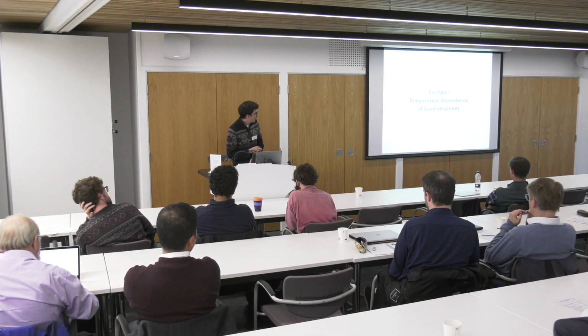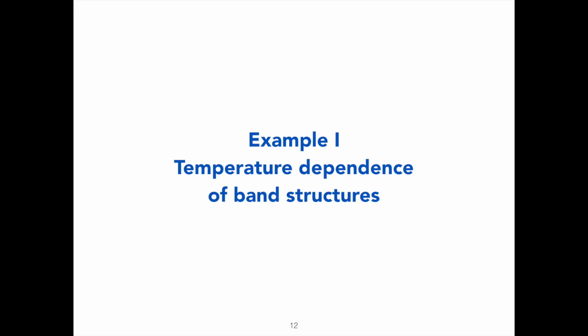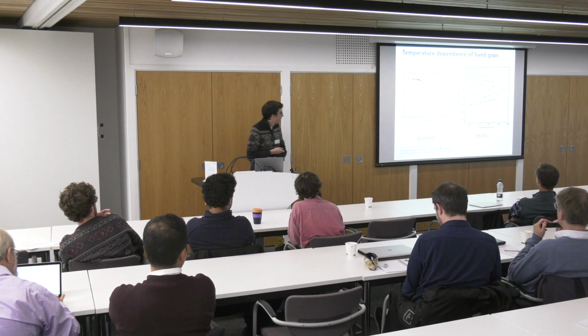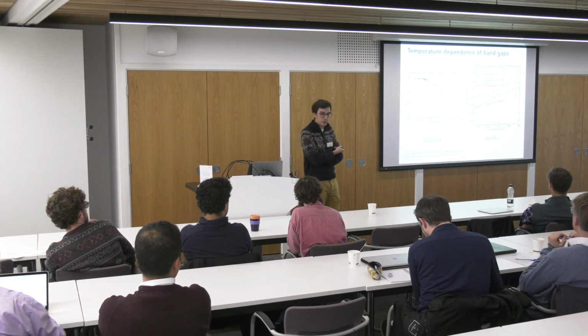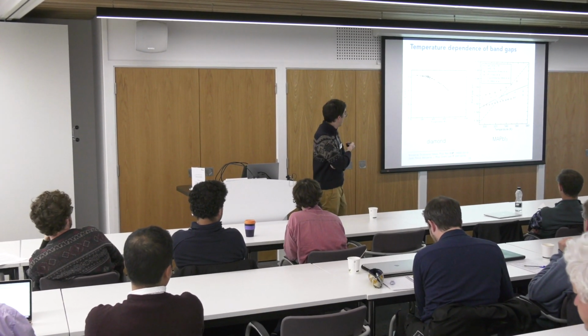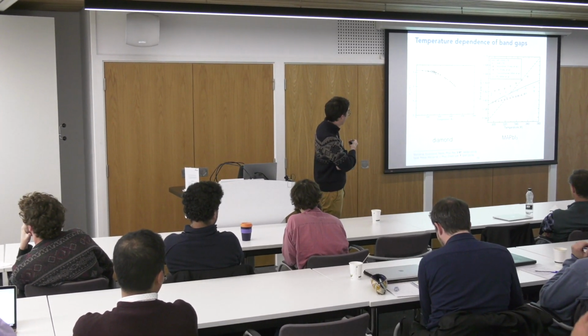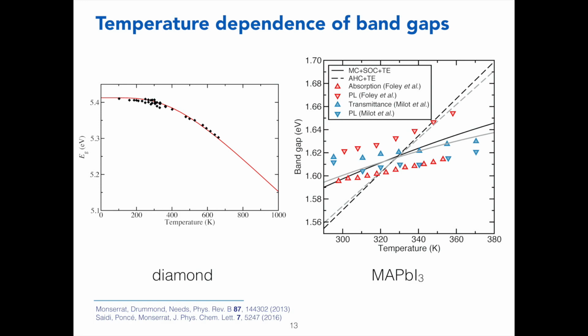So the very first one is just perhaps the simplest of all phenomena, which is the bare temperature dependence of the band structures themselves. And I want to show this just to convince you that what we do does indeed have predictive power. So what I'm doing here is I'm showing the band gap of a material on the vertical axis as a function of temperature on the horizontal axis. And on the left, I'm showing a relatively simple material, diamond. The red curve are our calculations, and the black diamonds are experimental results. So you can see they're really spot on.